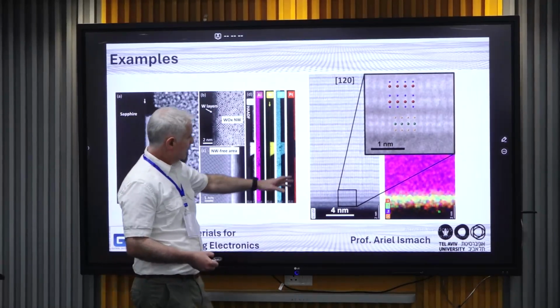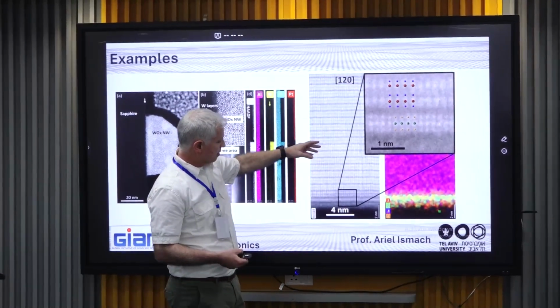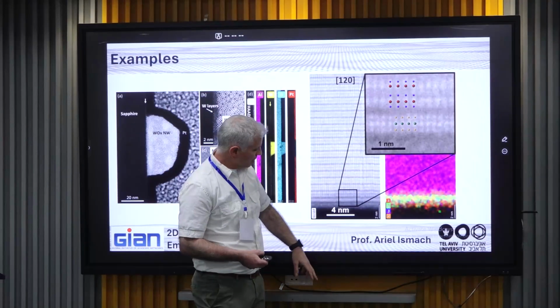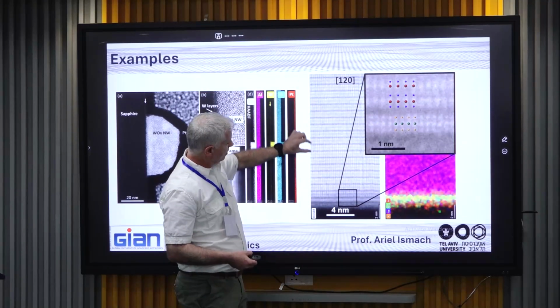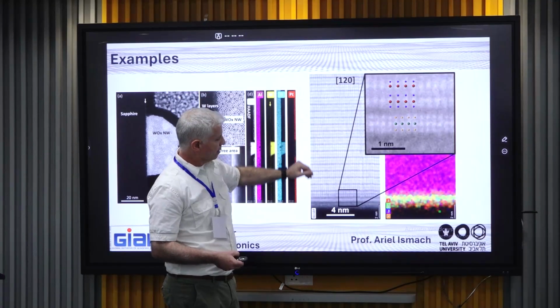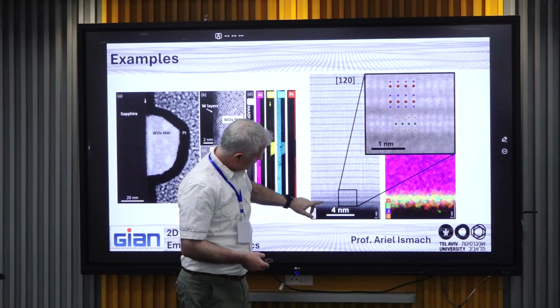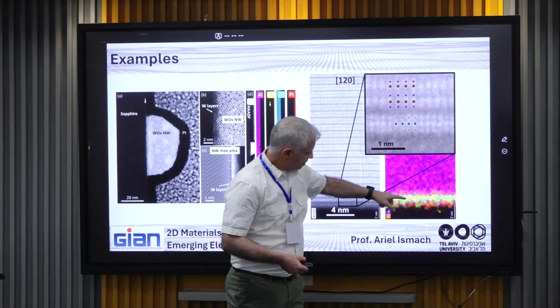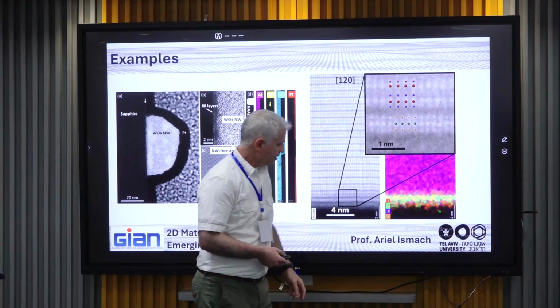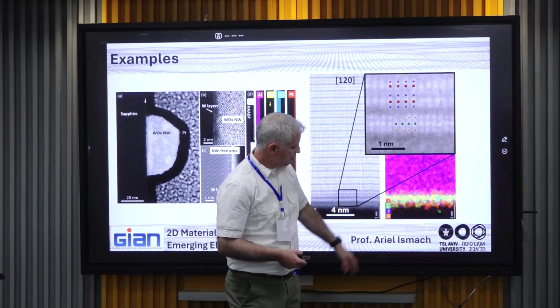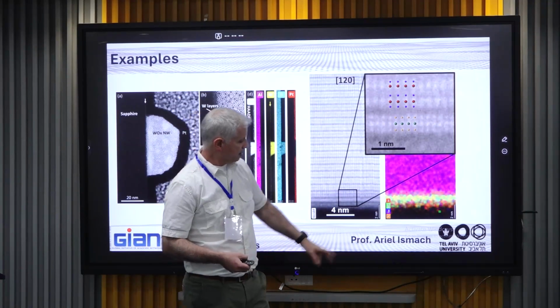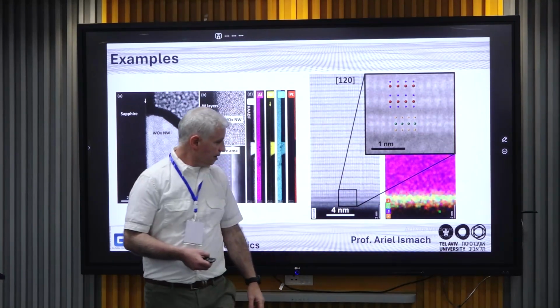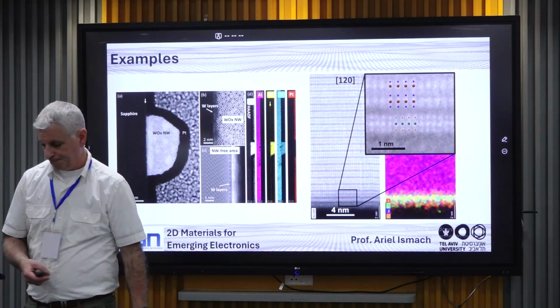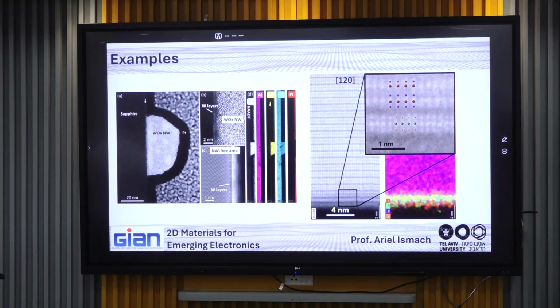And here another example of axial indium selenide on top of MoS2. So the indium selenide is this multi-layer crystal, and the MoS2 is here at the bottom, and it's easily seen by the mapping of the elements, as you can see here, molybdenum and sulfur only at the bottom. Sir, this is cross-sectional TEM, right? Cross section, yeah. Please explain how to prepare the sample.